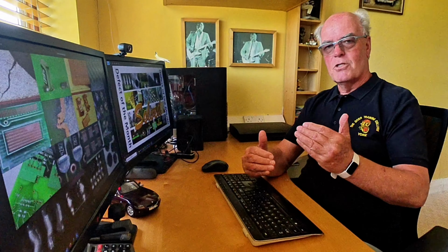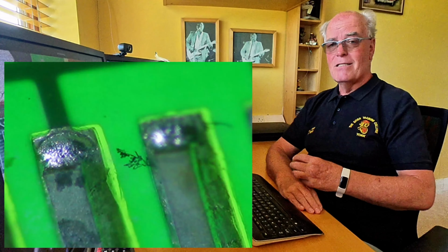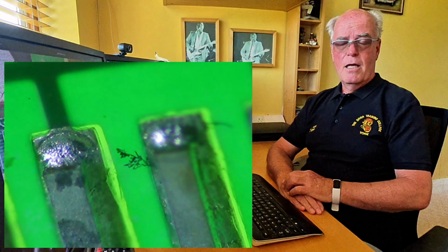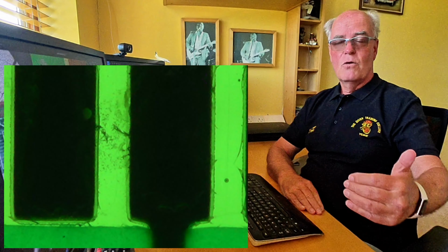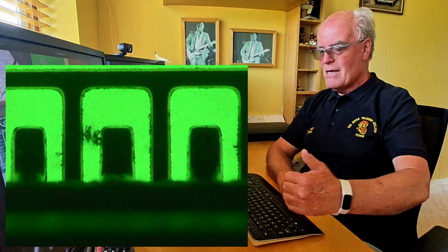This photograph, which is actually a video, shows how the condensation is slowly increasing on the surface. Based on the work that NPL have done, they can define how much condensation is taking place on the surface. That then allows them to estimate the difference in reliability of a product which possibly has gone through a process with a particular type of flux, or it's using some other metallization on the board, or some other temperature on the printed circuit board. It also allows you to look at the sensitivity of smaller and smaller surfaces.